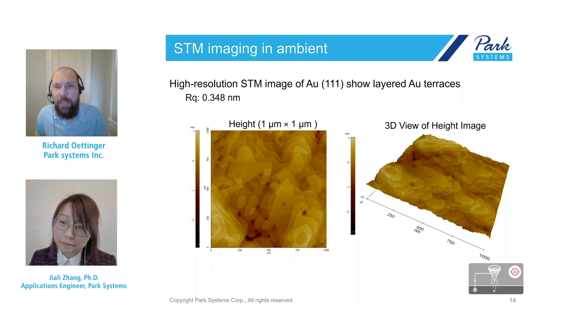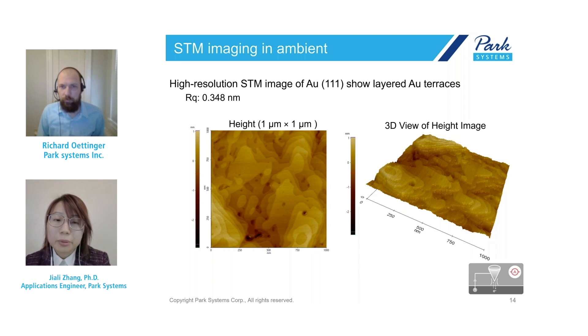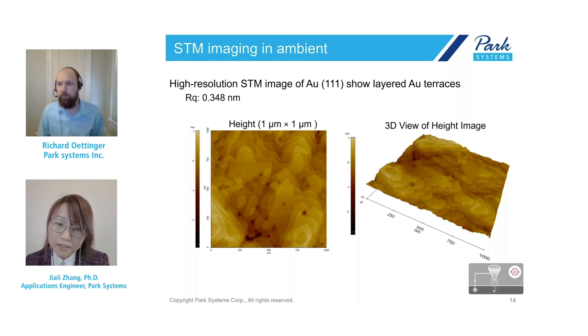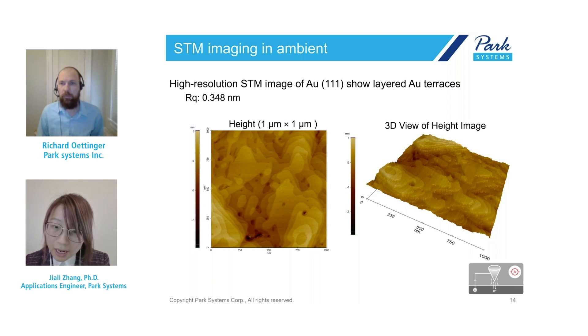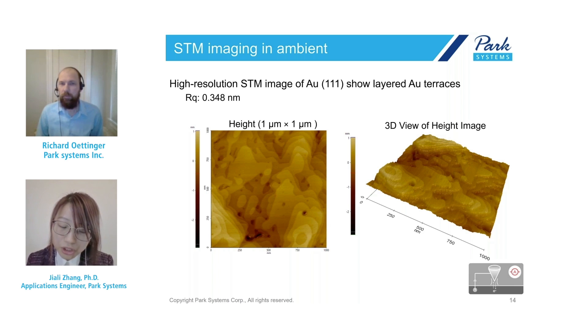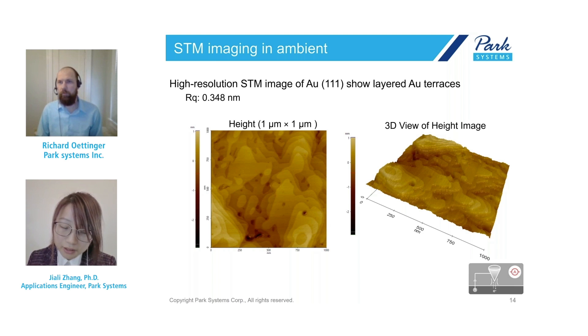Question: how do you calibrate your scan piezo — by taking HOPG atomic images, and would calibration change with tip length? We do have a calibration sample, but not HOPG. We use what is called a 100 nm standard — a prefabricated height calibration standard with a height of about 100 nm, consisting of silicon oxide structures on a silicon chip. The silicon oxide structures have 10 µm or 5 µm features used for XY axis calibration. Calibration is conducted periodically to ensure the AFM scanner works with high precision and accuracy. Tip radius should not affect the calibration.